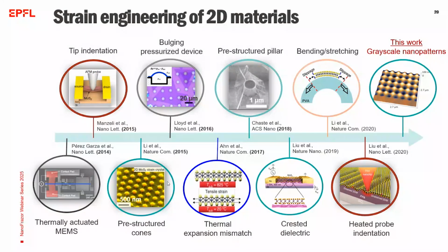So to induce strain in 2D materials, several techniques have been used so far, and this includes integrated MEMS systems, tip indentation, bending, stretching of flexible substrates, bulging devices, thermal expansion mismatch, straining on pre-structured substrates, as you can see in these cases. And among all of these techniques, strain on pre-patterned substrates has attracted significant interest due to its potential not only for achieving high strain, but also their scalable, industry compatible integration possibilities.